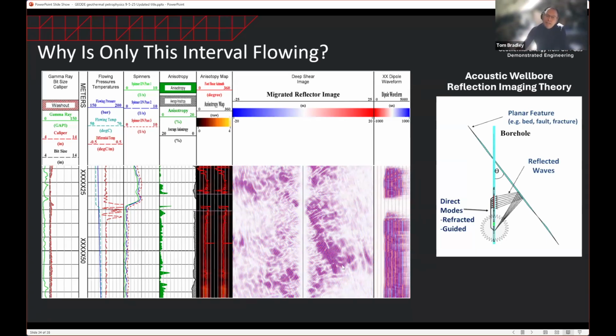And what you might see straight away is your eye might be drawn to this feature here. You have a strong reflective feature. If you project it to where the borehole is, it just happens to intersect the borehole at exactly the depth where all this flow is coming in. So how can we interpret this? Is this potentially an open fracture or fault, bearing in mind this is a carbonate prospect, where all the flow is coming from? So even with limited data, just an NMR log and a borehole acoustic log, we've started to derive a lot of important information telling us why all the flow is only coming from one depth.